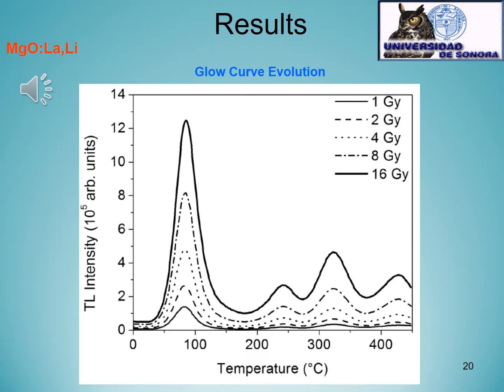There is a glow curve evolution for different doses for this material in the interval from 1 gray up to 16 grays. So we can observe that there is no evidence of saturation in the studied interval.